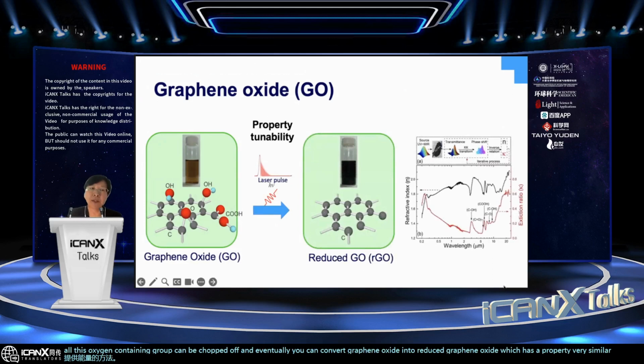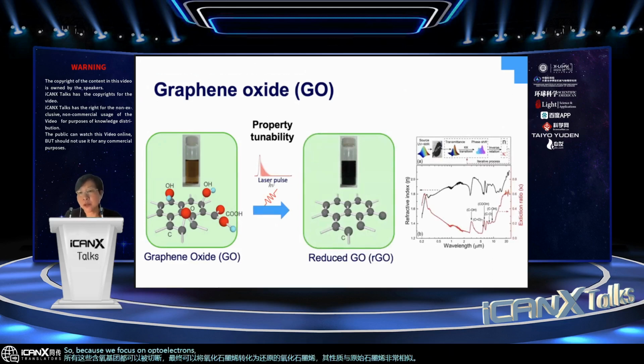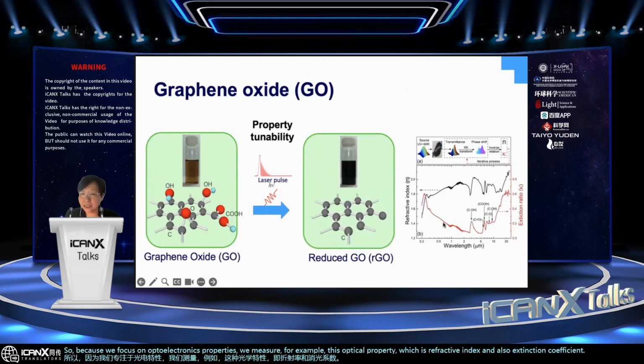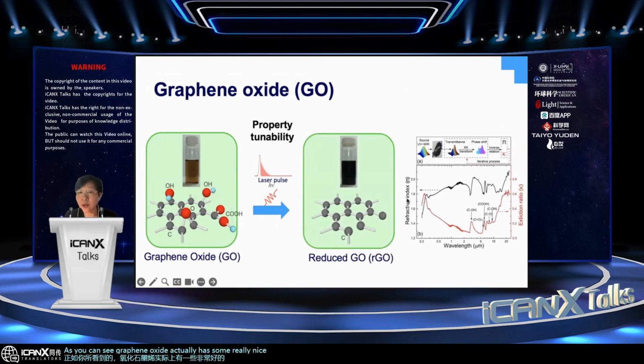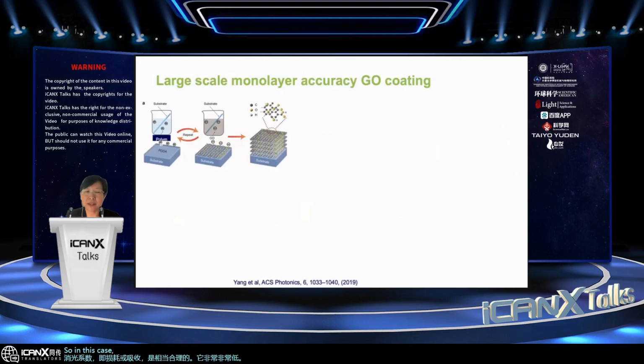Because we focus on optoelectronic properties, we measure, for example, this optical property, which is refractive index, and also extinction coefficient. As you can see, graphene oxide actually has a quite high refractive index, and also in a large range, the extinction coefficient, which means loss or absorption, is quite reasonable. It's very, very low. So in this case, we are thinking we can actually make use of this graphene oxide to make some large scale films.